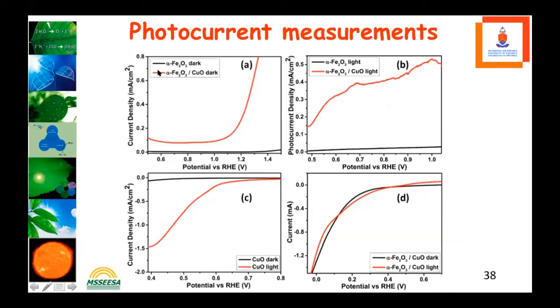You can see that in the photocurrent measurements here, you can't see the dark current of iron oxide because it's so low, it just became a flat line. But for the heterostructure, you can see it's a very nice curve for solar energy purposes.